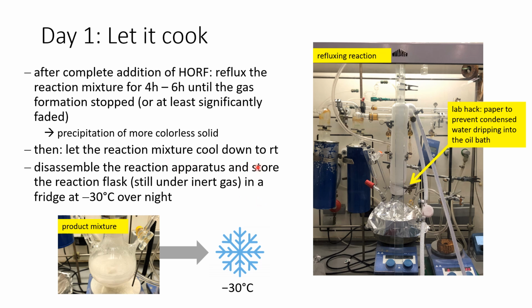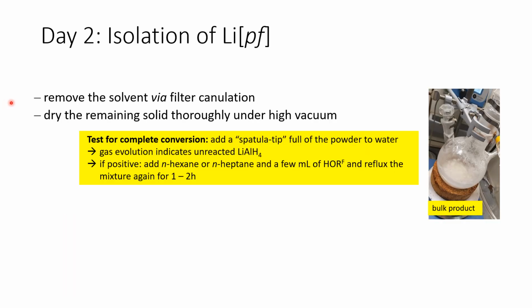Then, after the hydrogen evolution has stopped or at least significantly faded, we let the reaction mixture cool down to room temperature. Finally, we disassemble the reaction apparatus, close the reaction flask, still under inert gas, and put it in the freezer at -30 degrees overnight. During this time, we see a lot more precipitation of a white solid. The next day, we can simply remove the solvent via filtration. Then we should dry the remaining solid thoroughly under high vacuum to isolate our lithium salt.